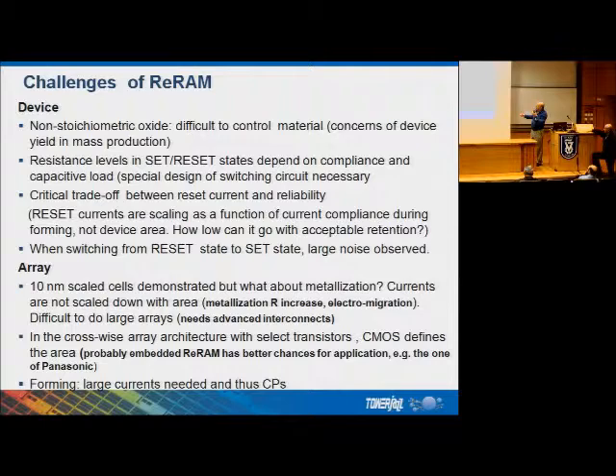So what are the challenges? What are the challenges for these memories? First of all, it is difficult to control the material. Resistance levels of set-reset states depend strongly on compliance and capacitive load during switching. There is a critical trade-off between reset currents and reliability.